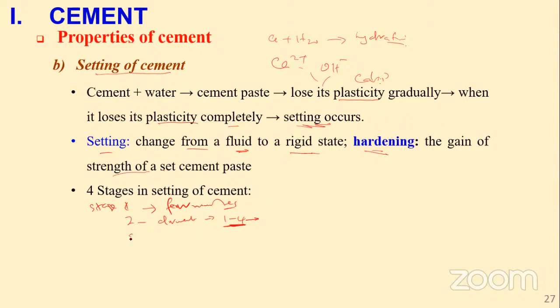Okay, so the third stage, again, we understood the dissolution of the weak layer, calcium hydroxide, when it settles out, precipitates, and the silicate precipitates. So we are saying the four stages still follow the stages that we found in the heat of hydration. So the third stage is in this part. And the fourth stage now here, hardening has started, strength gain has occurred. So we are saying the third stage takes about 6 hours for cement paste to start stiffening. And at the end of the stage, we have the final setting.